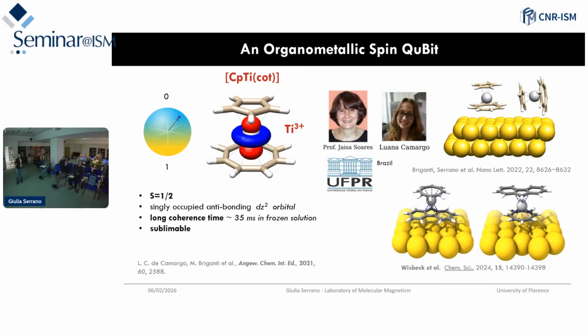And we measure quite a long coherence time that corresponds to 35 milliseconds in frozen solution, which is quite a high coherence time, also in the panorama of qubit coherence times. The nice thing is that Giulia's group can also modify the ligand a bit, for example, to create this complex with the fluorenyl ligand that can stick better to the surface. Of course, this system can be sublimated at room temperature, so you just open the valve and let them fly